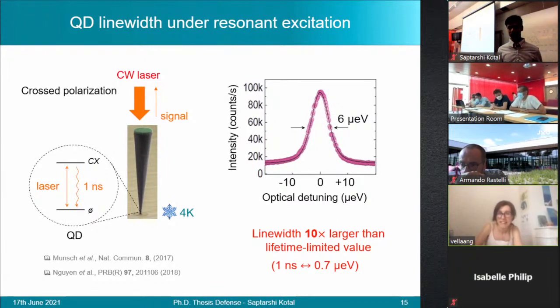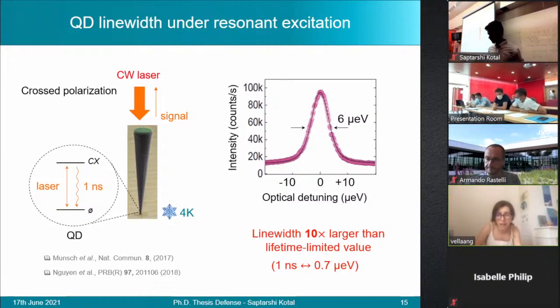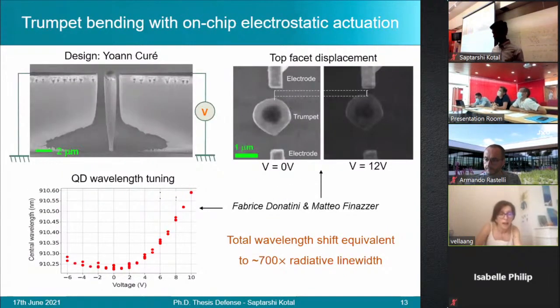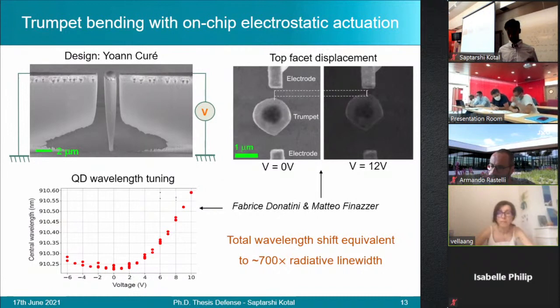So this contactless tuning. In particular, I would like to start about the simulation you did with Comsol. So you simulate the electrostatic force. You calculate this electrostatic force acting on the trumpet. And in figure 4.5 of your manuscript, there is the dependence of this electrostatic force as a function of the distance of the two electrodes. And this was calculated for a potential difference of 50 volts, so it was positive. So my question is, did you calculate this electrostatic force also for a negative voltage? What is the change in the optimization you can see when you change the polarization?